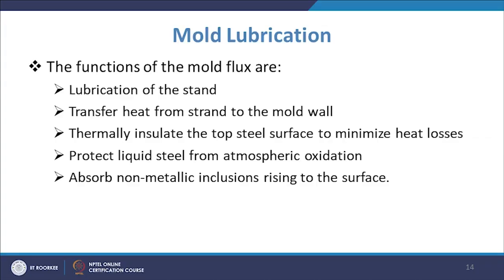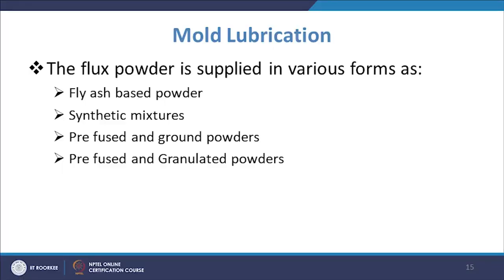The functions of these mold fluxes are that there will be lubrication of the strand, then they transfer heat from the strand to the mold wall, and thermally insulate the top steel surface, protecting the surface from atmospheric oxidation, as we have discussed. And many a times they absorb the inclusions, because if inclusions go up, that powder will attract those inclusions. That is another advantage of this mold lubrication mechanism. We use it in different forms, like fly ash based powder, synthetic mixture, pre-fused and ground flour powders, and then granulated powders also. That way we give this mold lubrication.